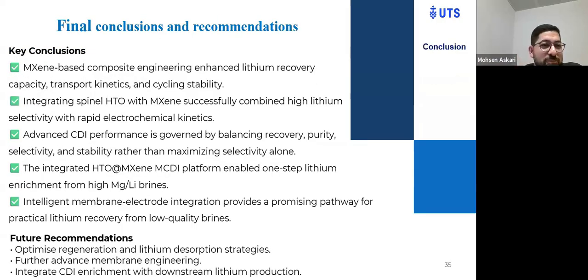Final conclusion and recommendation. The key conclusion is that MXene-based composite engineering enhanced lithium recovery capacity, transport kinetics, and cycling stability. Integrating spinel HTO with MXene successfully combined high lithium selectivity with rapid electrochemical kinetics. Advanced CDI performance is governed by balancing recovery, purity, selectivity, and stability rather than maximizing selectivity alone, which is usually reported. The integrated HTO@MXene MCDI platform enables one-step lithium enrichment for high magnesium-to-lithium brine. An intelligent membrane electrode integration provides a promising pathway for practical lithium recovery from low-quality brine.